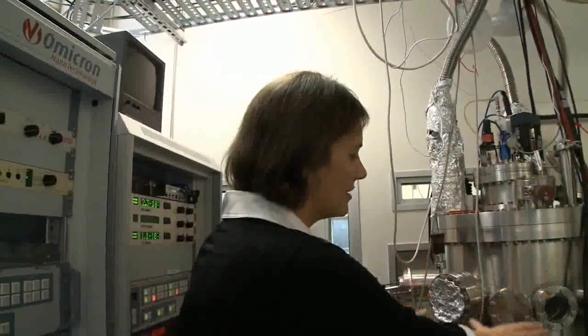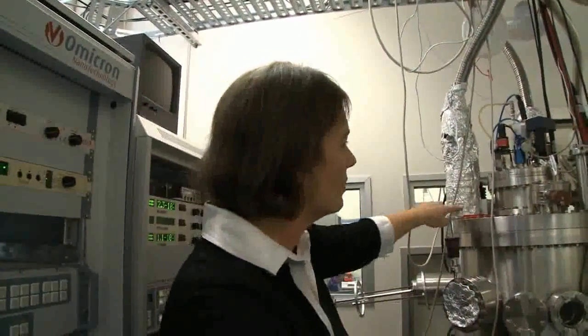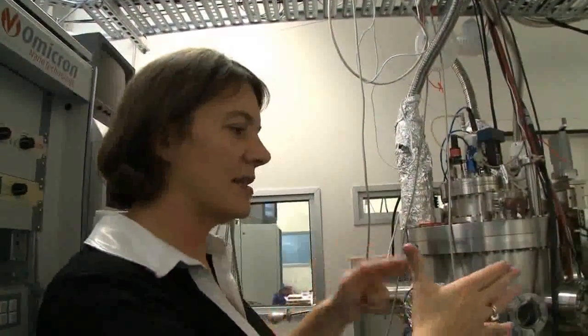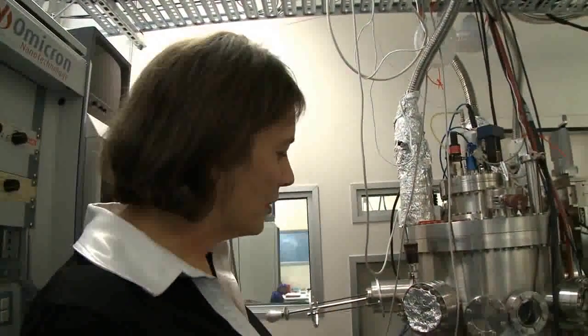And ideally, what we want in this crystal growth system is for the pressure to be as low as possible. So when we heat the silicon up, the only thing that's coming towards our surface is silicon, nothing else. We don't want any impurities. And the way that we do that is we have this thin skin inside the UHV system which goes up to a big tube that's hooked up to a liquid nitrogen tank. So we literally run liquid nitrogen through here 24 hours a day, 7 days a week. And that's really, really cold. So any other atoms that are floating around in that vacuum system stick to the walls, and they don't go into the crystal. So the pressure gets really, really low. And we also have shutters on each of these controllers here that sit across the silicon cell. And we can open the shutter for very short periods of time and literally grow one atomic layer of silicon at a time.